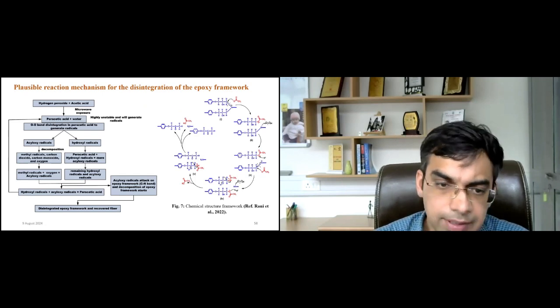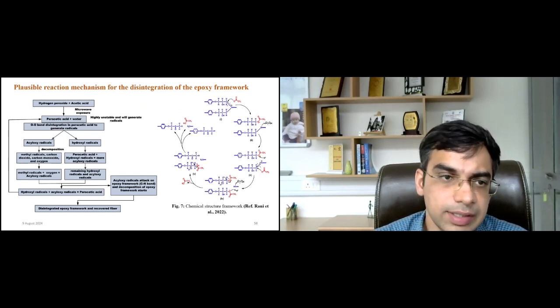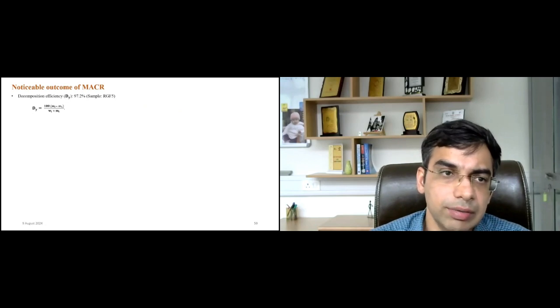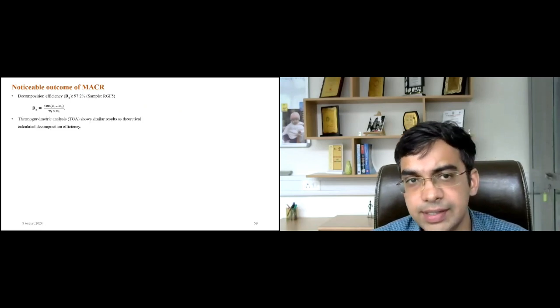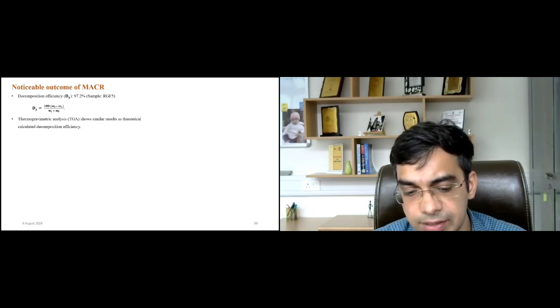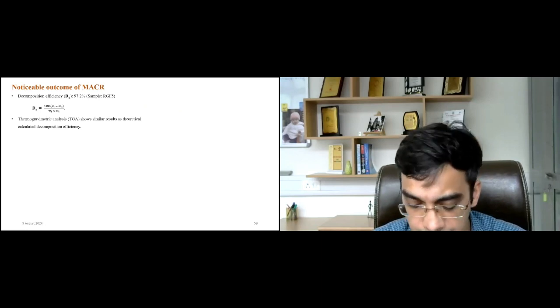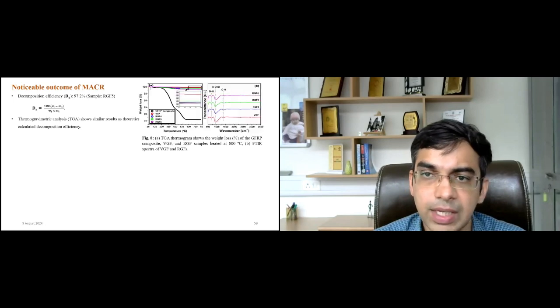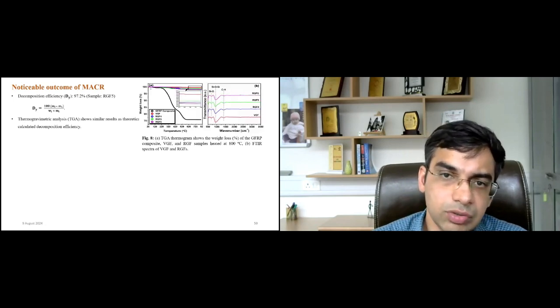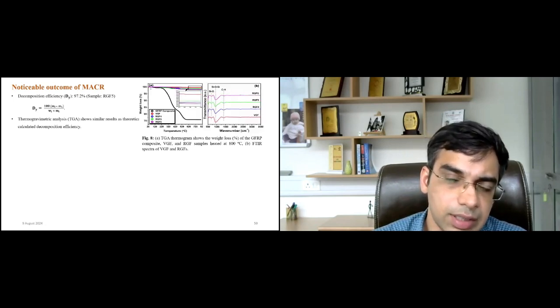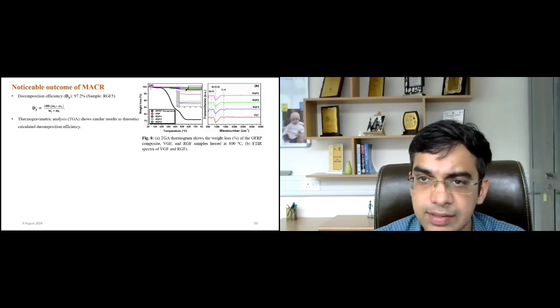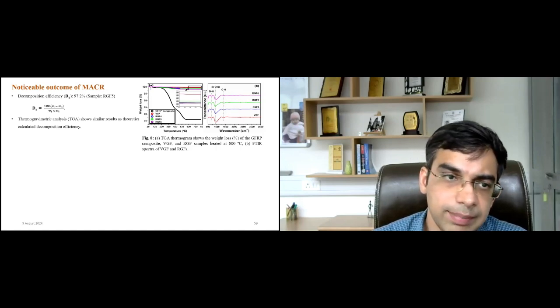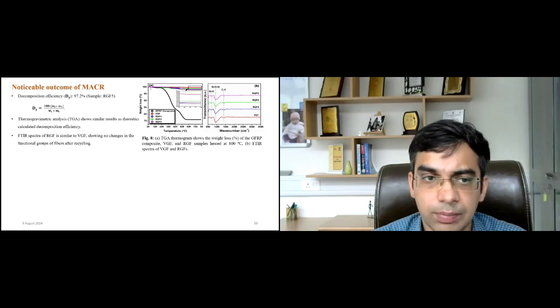This is already published in reputed international journals. We also looked at the decomposition efficiency in our case. Under specialized, optimized conditions, a decomposition efficiency of approximately 97% was achieved. We also compared it with the virgin glass fibers, that is, the unrecycled glass fibers, and similar TGA results were obtained.